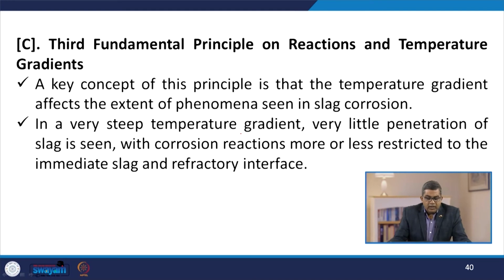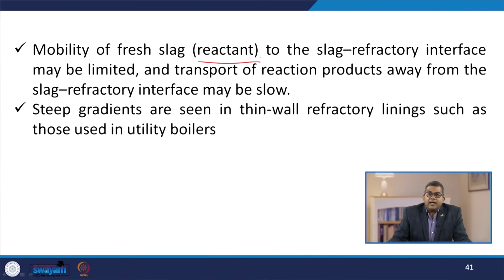Now, the third fundamental principle is reaction and temperature gradients. A key concept of this particular principle is that the temperature gradient affects the extent of phenomena seen in the slag corrosion. Now, in a very steep temperature gradient, very little penetration of slag is seen, with the corrosion reaction more or less restricted to the immediate slag and refractory interface. The mobility of fresh slag, sometimes referred to as a reactant, to the slag refractory interface may be limited, and transport of reaction products away from the slag refractory interface may be slow.